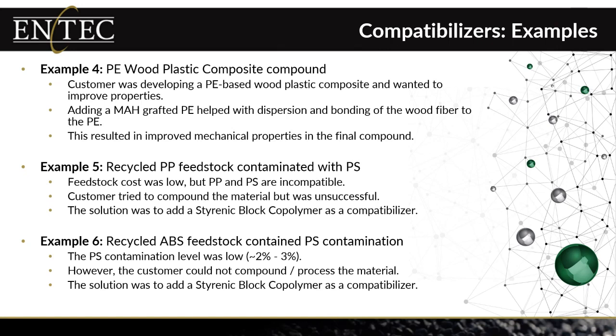A lot of people make wood plastic composites, especially out of polyethylene and wood flour. Typically here we would add a maleic anhydride grafted polyethylene, not only to bond that cellulose wood fiber to the polyethylene, but it can also help a bit with the dispersion, because once again, it's going to reduce that interfacial tension, and that can help with dispersion, and that results in improved mechanical properties. And in this case, it's often used more as a coupling agent, really at low loading levels like 2 or 3% versus a little bit higher levels as a compatibilizer.